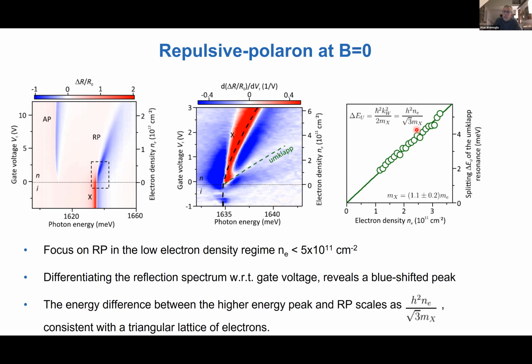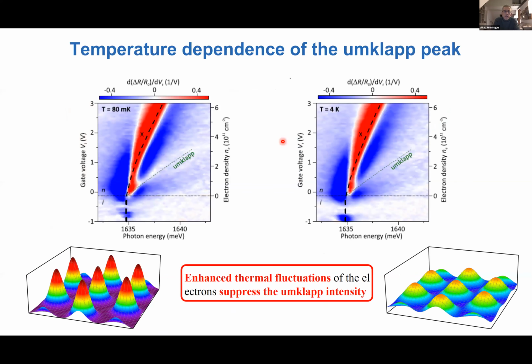So the fact that we have this very nice linear dependence of the splitting of the umklapp from the main exciton line is our first strong indication that this peak is not some spurious peak, but really could be linked to the formation of a Wigner crystal. So to get further, maybe I should stop here.